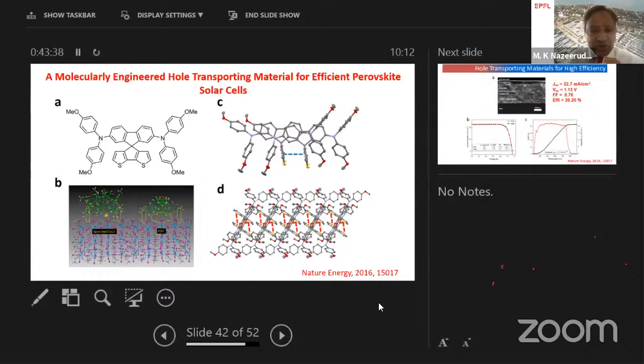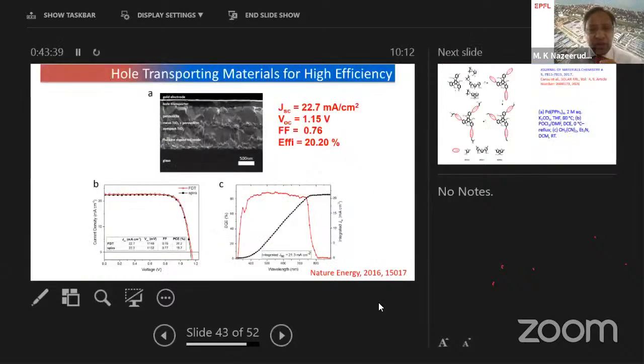The next slide shows the power conversion efficiency. Yes. So here is the power conversion efficiency and the cross-sectional image of the perovskite solar cells, in comparison with spiro-OMeTAD. Comparable results were obtained. The beauty here is to have these thiophene groups for a better interaction with the interface. So can we further modify these hole transporting materials so that we don't have to dope at all? The next slide shows the new design concept.